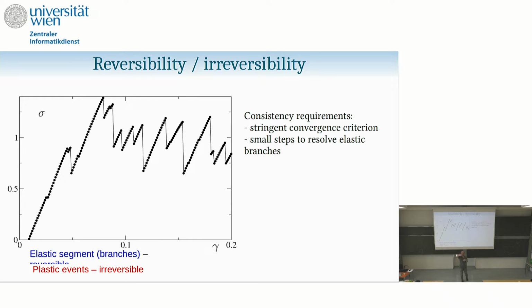Of course, if you take very big strain steps, you might miss all the interesting information, and then what you do is nonsense, right? So the problem is you need to have small enough strain steps so as to resolve the continuous elastic response, and then you have these local plastic events that you resolve.